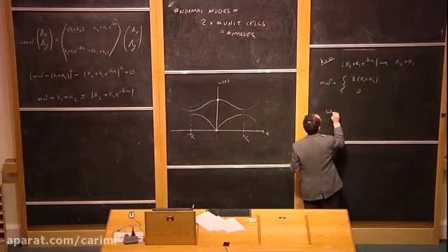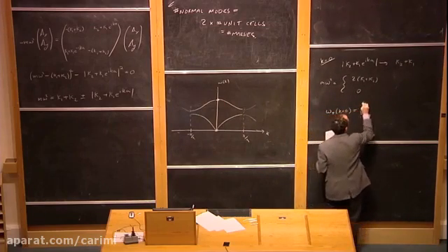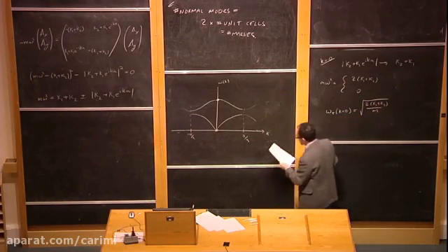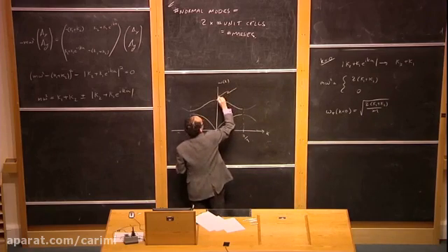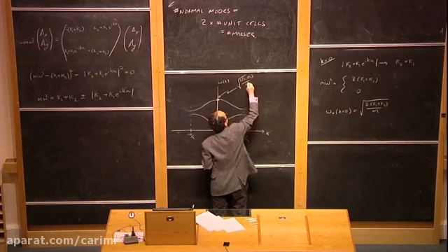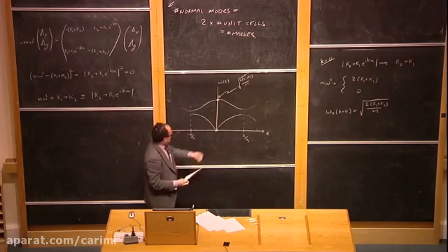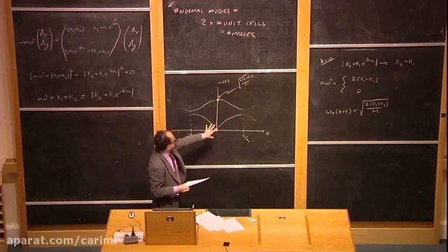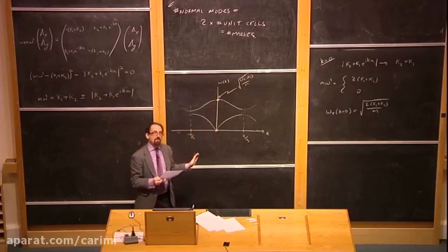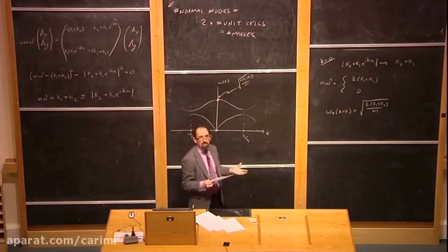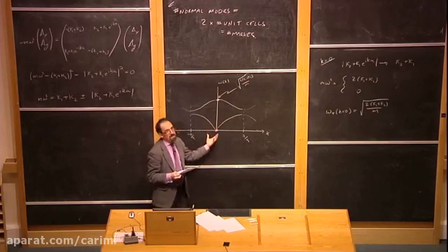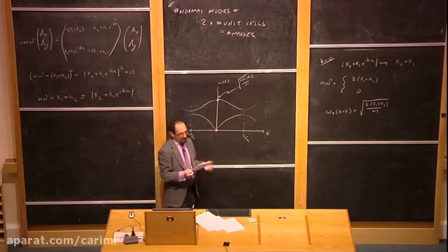So omega plus at k equals 0 is the square root of 2 times kappa 1 plus kappa 2 over m. Did I get that right? I think so. So that point here, we'll give it square root of 2 times kappa 1 plus kappa 2 over m. And so we have the low energy mode and we have the high energy mode. Now, we'll come back to the high energy mode in a moment, but the low frequency mode is one that we should expect should have been there, because we should expect that there should be sound waves somewhere in this system. And when there are sound waves, we know the sound waves should have a spectrum which has frequency linear in wave vector and comes down to 0 at 0 wave vector.